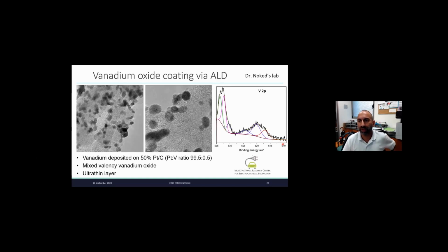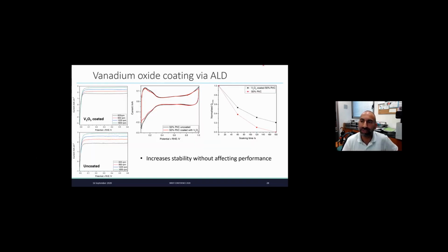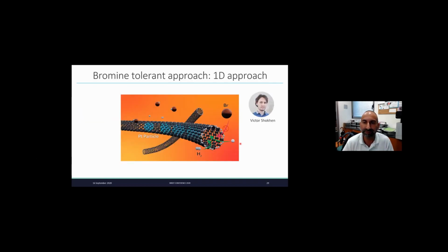And we, in collaboration with Dr. Noked's lab, so we did some use of atomic layer deposition to coat some vanadium oxide. We don't see the vanadium oxide on top of the particle, maybe because it's too thin. We have to look into it. We do see some vanadium by XPS. The good thing about the vanadium is that we see some improvement, but not as good as the Titania as we did before. So I think that we have room to improve this technique.